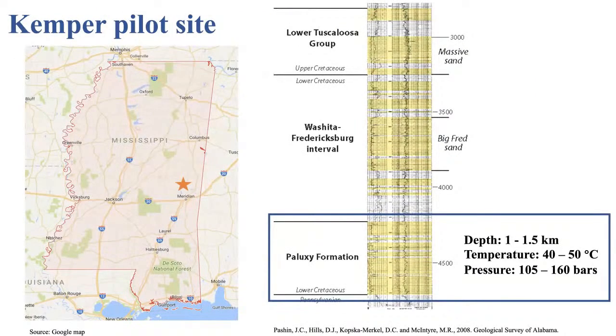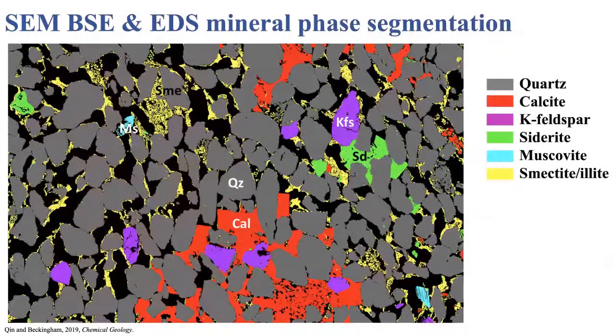Here we used a sample from the Paluxy Formation, which is a potential pilot CO2 injection plant in Kemper County, Mississippi. We used SEM imaging to determine the distribution of minerals within a thin section. And so here, each color corresponds to a different mineral phase. This sample is predominantly quartz, but does have some reactive calcite shown in red, as well as some clay, smectite illite in yellow, as well as feldspar minerals.